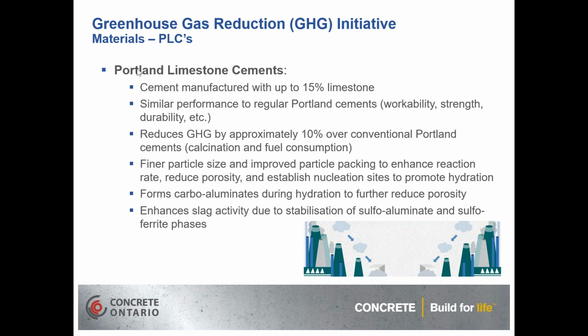Now, typically, the Portland limestone cements are a little bit finer in the particle size, which helps improve the particle packing, and that enhances the reaction rate and establishes nucleation sites. It reduces the porosity of the cementitious hydration product matrix. And we also form carboaluminates from the carbonate from the limestone and the aluminates from the clinker during the hydration, which is going to help to further reduce the porosity. And on top of that, the Portland limestone cements tend to work very, very well with slag and SCMs because of that carboaluminate reaction, where you've got more aluminates available from the SCMs, and they stabilize the sulfoaluminate and sulfoferrite phases.